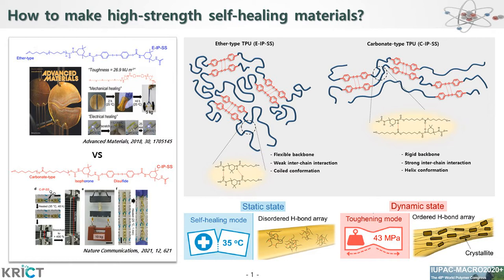Although these TPU show higher strength and toughness than similar self-healing materials, the strength of TPU typically used in real life is over 40 MPa. Therefore, it is noted that the strength of TPU is still far below that of commercial urethane. In the present study, we developed TPU consisting of carbonate-type polyols instead of usual ether-type polyols. This material is capable of self-healing at body temperature with strength similar to that of commercial urethane.